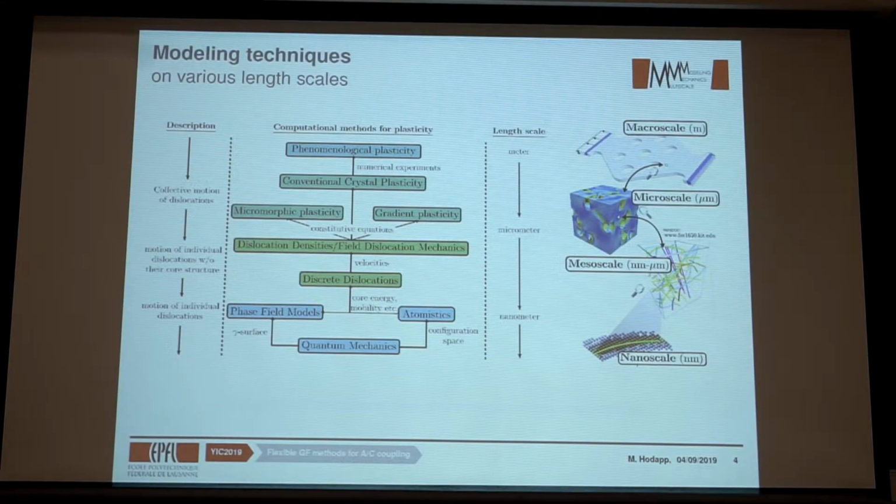And with discrete dislocation dynamics, you can do even more. You can compute very large dislocation networks in microspecimens. You can then load these samples, and you can actually compute effective properties in order to compute strain curves, etc., with which you can then, in the end, calibrate your macroscopic crystal plasticity or phenomenological plasticity law.